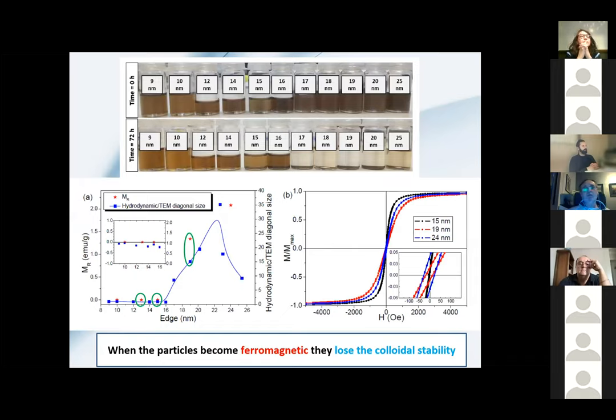And then we transferred them to water to see if they were stable with time. This here is just after we transferred them to water, and they are colloidally stable. However, when we wait a few days, you see that the samples with the largest nanoparticles precipitate down here, but the samples with 16 nanometers or less are colloidally stable even after 3 days.